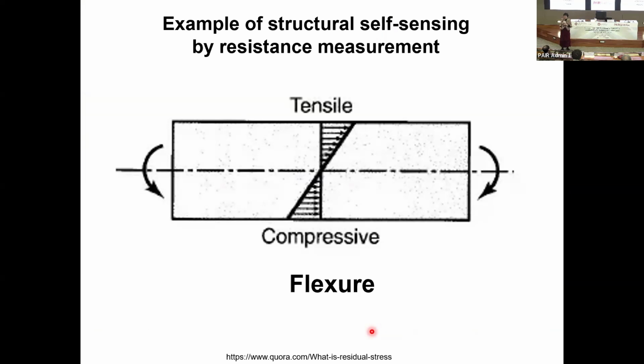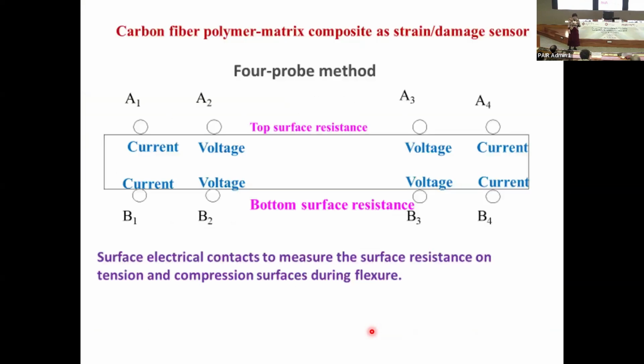Here's just one of the examples of structural self-sensing by resistance measurement. This is under flexion. Okay, and one side is feeling tension, the other side is feeling compression. And we can sense both sides separately and simultaneously by measuring the surface resistance on either side. For each side, we apply 4 electrical contacts, the outer 2 for sending in current, the inner 2 for measuring the voltage. And so the top surface resistance and the bottom surface resistance get measured.